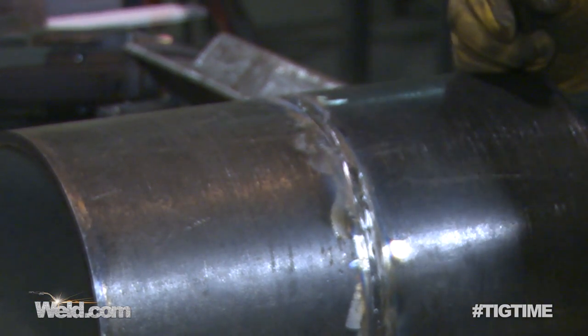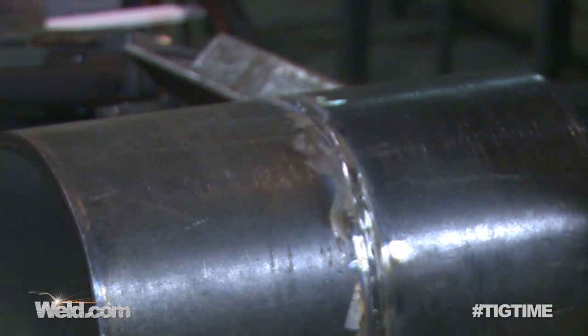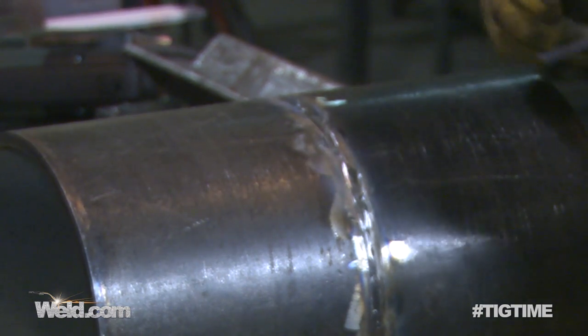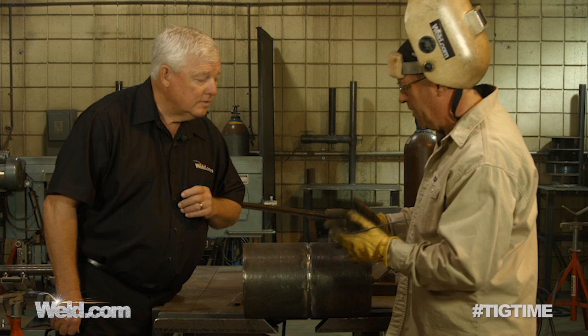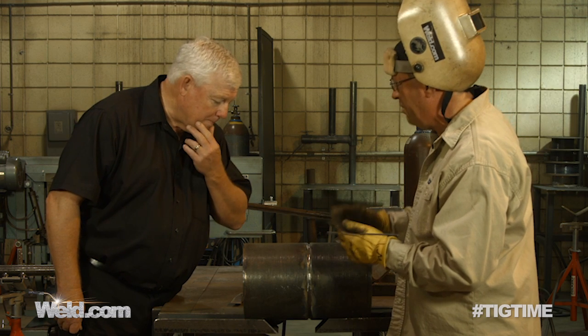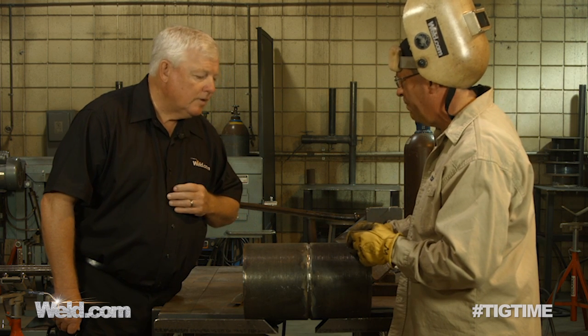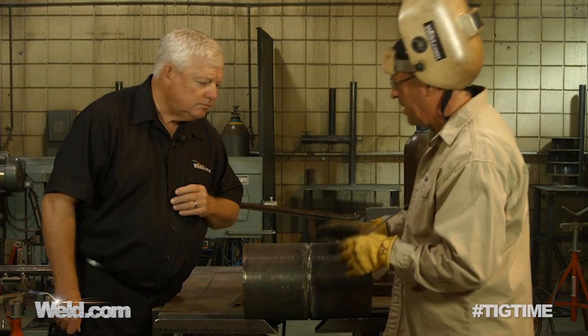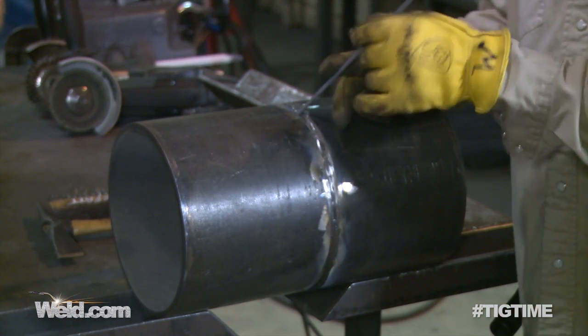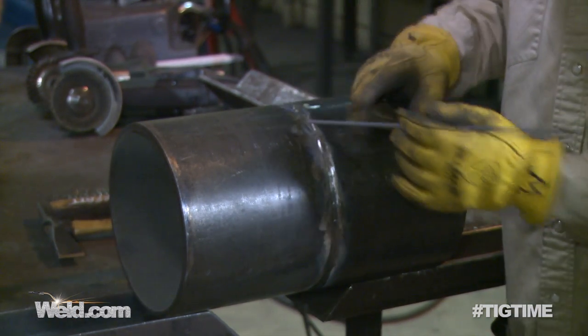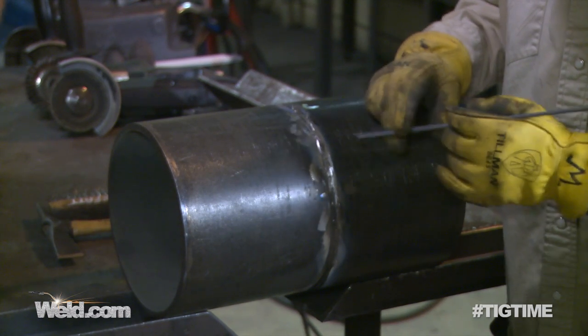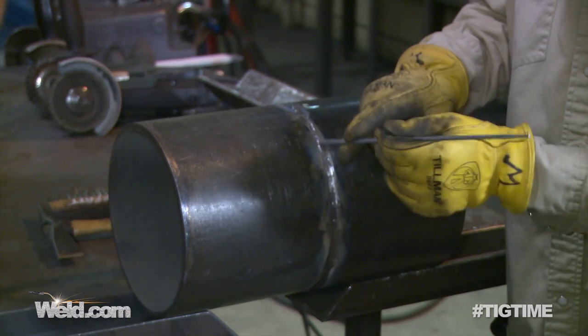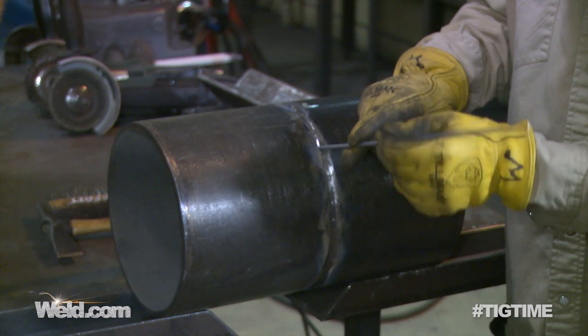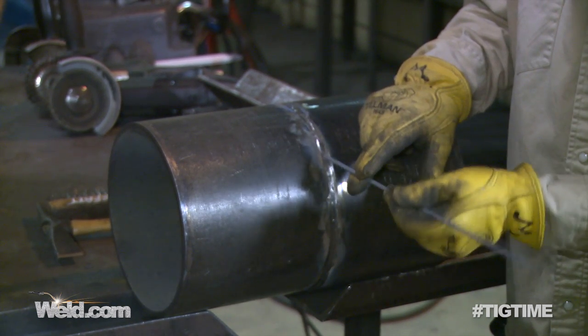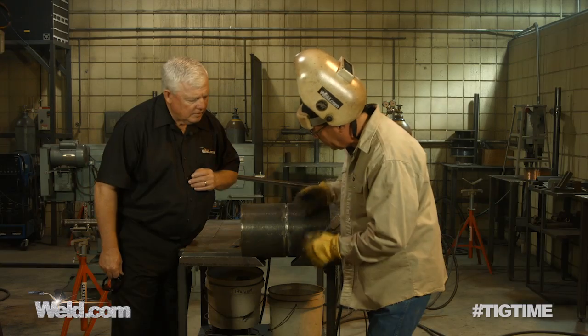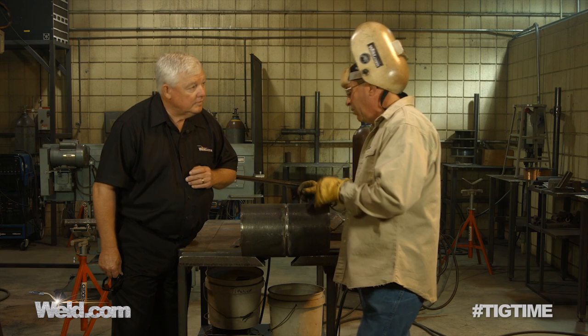That's fine by me, because I know I can blow this out of here. That's what I'm going to do here is run a hot pass, and that's what the hot pass is for, to get rid of that kind of stuff. So I'm going to run this hot pass, and I'm going to get these slag inclusions that are on either side of the root with the technique of dragging this down and lifting it up. And just a little stitch, rocking motion and a stitch. And that's going to get rid of all that stuff.